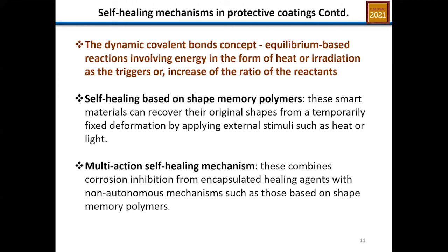You could also have self-healing based on shape memory polymers. These are polymers that can recover their original shape from a temporary deformation through the help of an external stimulus. And in recent times, we have been seeing a lot of works, and we have also tried to check some works, on multi-action self-healing. This is a situation where you combine the encapsulated material in the presence of shape memory polymers. So the scratch plane has the healing agents released into it, which provides a film that covers the scratch plane and prevents the ingress of corrosive ions, while the shape memory polymer heals the surface. You have a double healing that provides more passive behavior at the end of the day to the coating matrix.